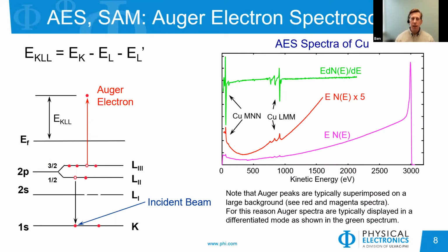The next technique is Auger electron spectroscopy, also called AES or SAM for scanning Auger microscopy. And it has a kind of similar method to it. Rather than having a photon hit the sample, we will be using an electron beam. So the incident beam will interact with the sample, knock out a core level electron. And then an electron from a higher energy level will fall in to fill that vacancy.